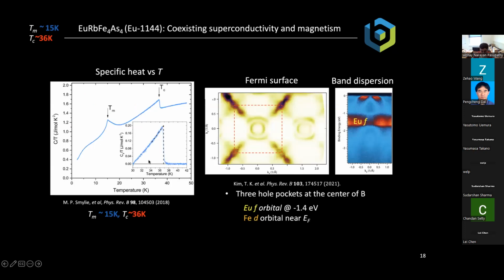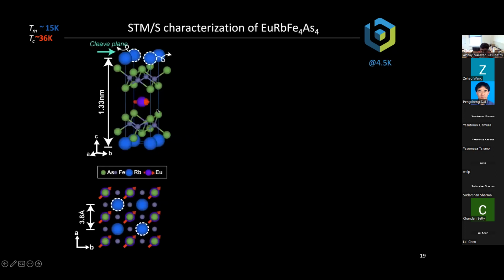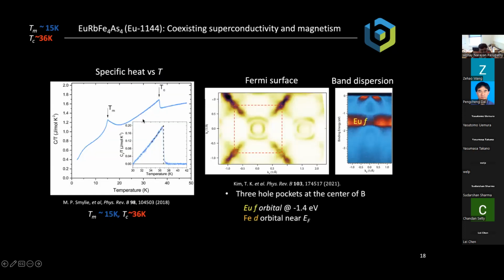Now, what's beautiful about this material, and there's a number of such materials, is that this material is also a superconductor at the same time as it is a magnet. And if you look at the heat capacity of this material, it shows a very clear superconducting transition temperature. This is quite high in temperature, around 36 Kelvin here. And as you cool down, interestingly, the magnetism sets in at a lower temperature. Magnetism in this compound sets in around 15 Kelvin. And you can again see the magnetic transition in the heat capacity very, very well.